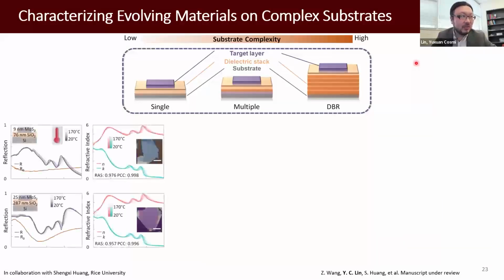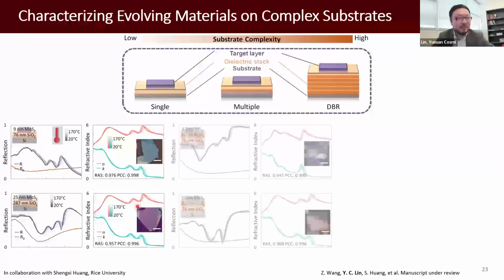This network was trained with a lot of optimization, so just to show you the results. We verified that this prediction works well for simple and complicated substrates. We use a single dielectric layer to demonstrate the simple substrate. The left-hand side is the reflectance measured. We vary the temperature of the system, and the MoS2 N and K also change. We use this as the input of the network, and we can predict how the N and K evolve with temperature for the same material.